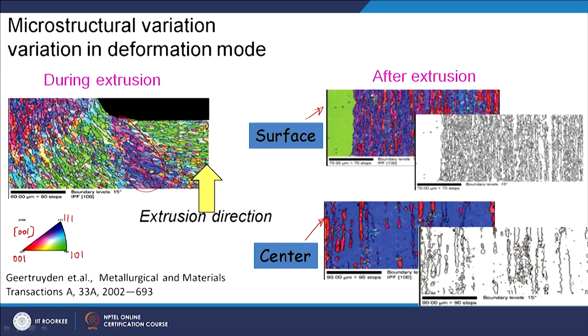And at the surface, the microstructure is more refined because maybe the strain is higher there. Also, you can see a very coarse grain structure here by this green colored grain, a very big grain is there. And the rest of them are very fine, that means more strain is seen by the surface and less strain is seen by the center. So, again a very nice microstructural variation you can see in the same extruded billet.